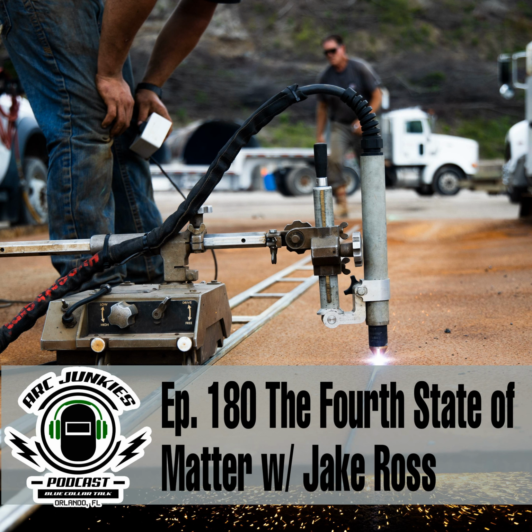And yeah, it's going to be a little bit slower, but we just did this test up at Ryan's shop. When you run the 45 amp versus the 85 amp and do a side by side and look at the angularity, I cut two squares of each amperage process and then butted them up against each other, and you'll see the difference in the gap. We were running quarter-inch material for that test, and that's where you see the visual effect.